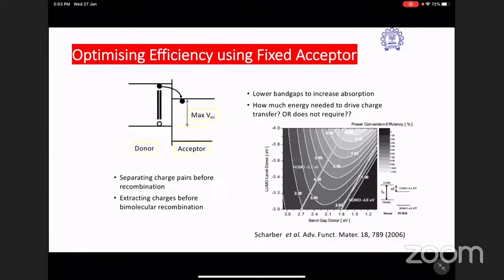According to the simulation, that is like 2006 when I was doing my PhD, and I thought, okay, 10% solar cell is the extreme, and once 10% is achieved, this OPV technology will be commercialized. And the idea was you reduce the LUMO of the donor. On the y-axis you see the LUMO of the donor and the band gap of the donor. You tune the band gap of the donor and the LUMO of the donor to minimize the voltage losses at the LUMO offset, and that will basically set the thing for you. And that was done.